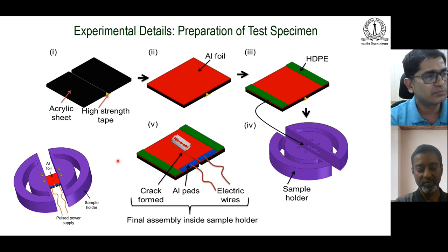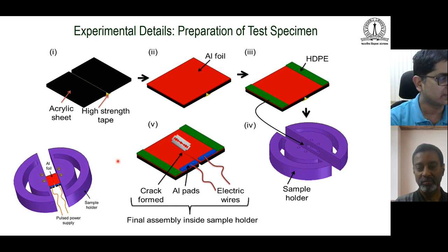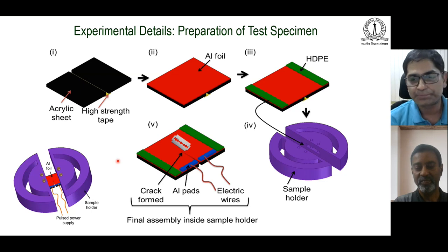Whereas when we do it at room temperature, in the ambience, then the temperatures may go close to 400 to 500 degrees Celsius for aluminum, which is very high actually. But that region is very small. That region is only a few tens of micrometers, over which the temperature goes back. Remember that we are doing these experiments on a foil for a reason, to maximize the heat loss. If we do these experiments on a thick sheet, then the temperatures will go very, very high, and it will become difficult to minimize melting, actually.